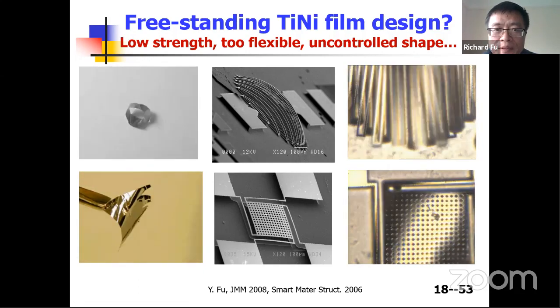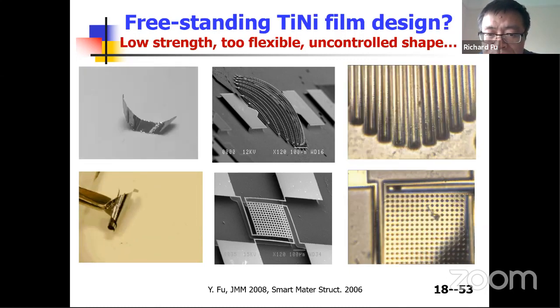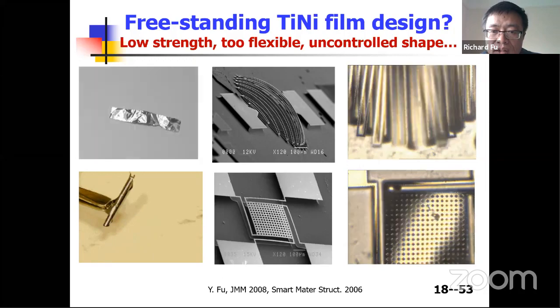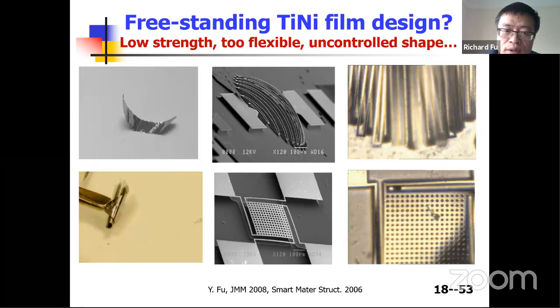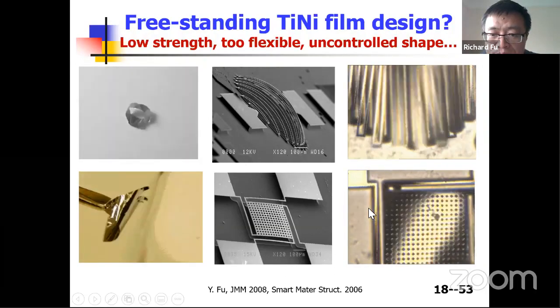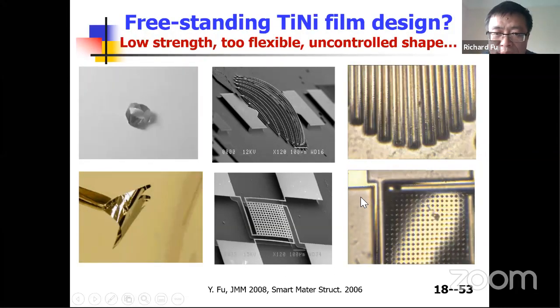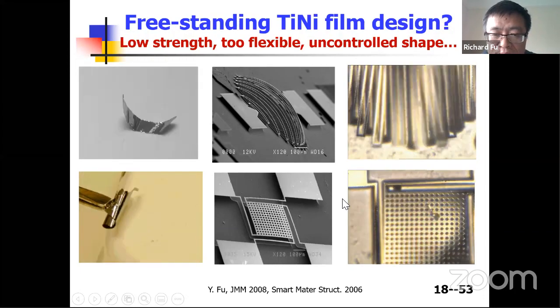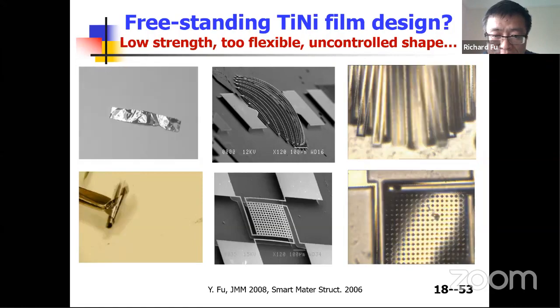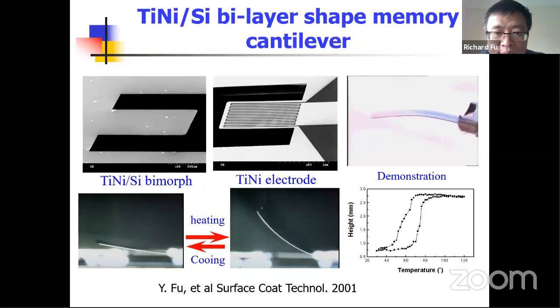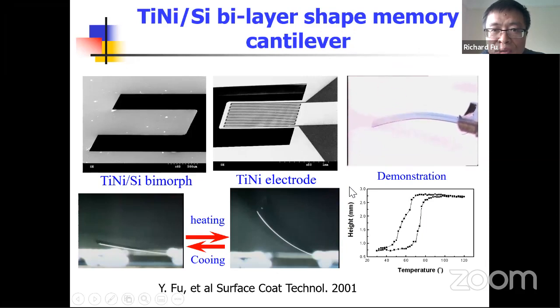But the problem with thin film is that it's only about 1 micron or a few microns thick. And this thickness has very low stress or strength to actuate the structure. So a freestanding film, unless it's at a very tiny micron or nanoscale, is very difficult to use to actuate a very large scale function. In that case, we need to design using a bilayer structure or bimorph structure. That means we can use silicon or other materials like metallic materials to make the two-layer structure.